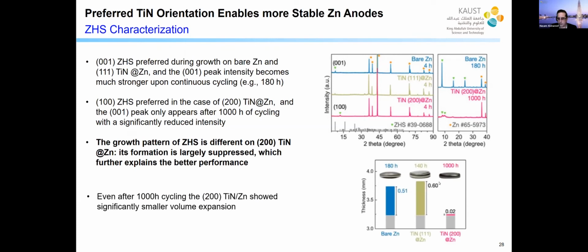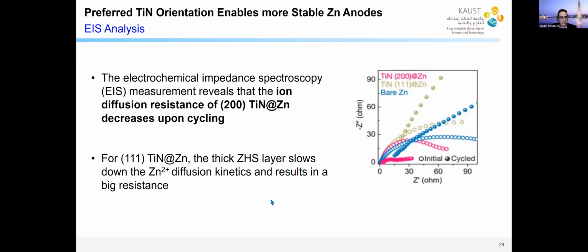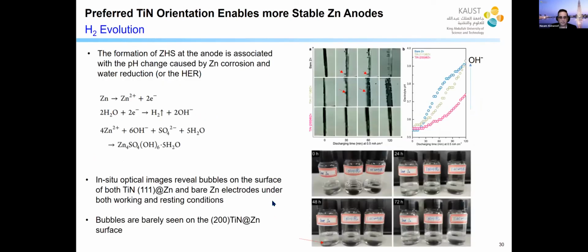And this is another visual illustration of the impact: bare zinc, 111 tinitride, 200 tinitride. You see the thickness change as a result of this byproduct. It's significantly suppressed in the case of the 200 tinitride. This also, by the way, affects the EIS. You see that the diffusion resistance, which is from the intercept right here, after cycling, which is the solid curves, is smallest for this 200 tinitride. This is because it forms the smallest amount of this second phase.